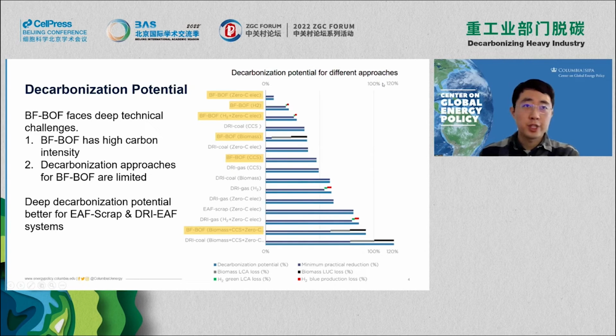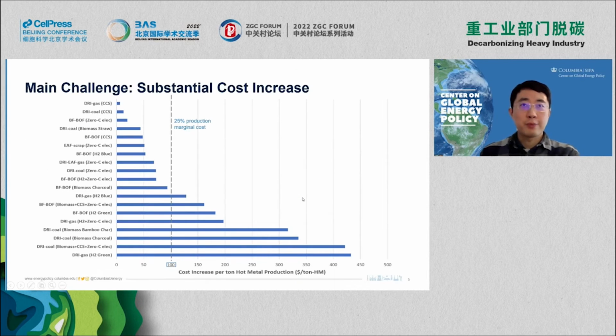So we will have a better chance to reach deep decarbonization and eventually net zero with EAF-based solutions, using scrap metal to produce recycled iron and steel, or using DRI, which has a lower CO2 intensity. Another concern is absolutely the cost, and it's actually the main challenge for any of the decarbonization approaches. Many of these approaches will have a production cost increase higher than 25%, and CCS is possibly the cheapest option compared with hydrogen, biomass, or electrification.